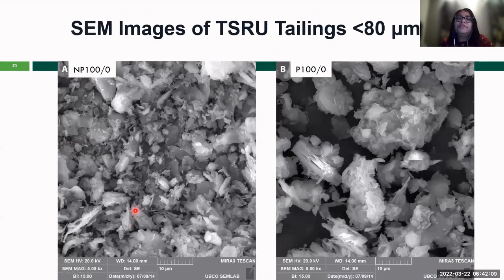Now we will look at the SEM for both the non-polymer and polymer samples that we have identified and tested in our lab. This is the image for the non-polymer, and this is the image for the 100% polymer. The main difference between these two materials is that we see the flock structure for polymer-amended tailings, which we don't see in non-polymer tailings. So this is a major difference in structure when we look at these SEM images.